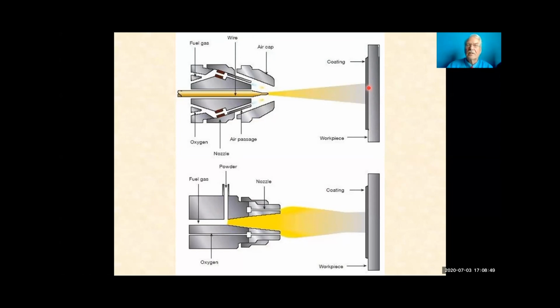Now this not only gives good adhesion for the coating, but it also provides a good substrate for subsequent paint. So it provides cathodic protection, it provides a good anchor for subsequent coats of paint, and for a long-term outdoor coating, it's very good. It's fairly economical to do, it can be done on site, and I recommend it.